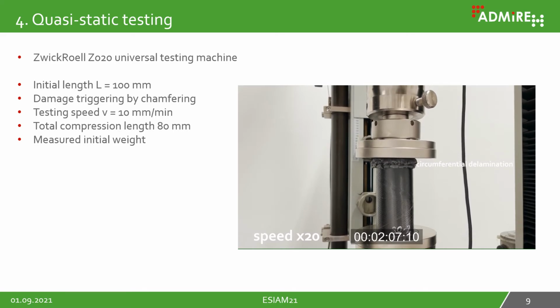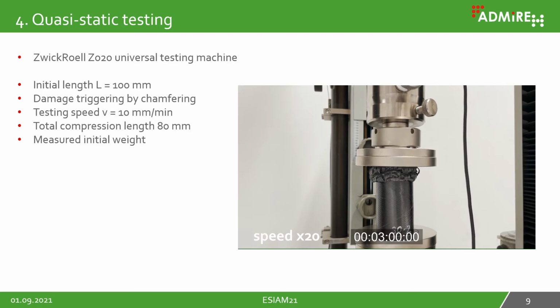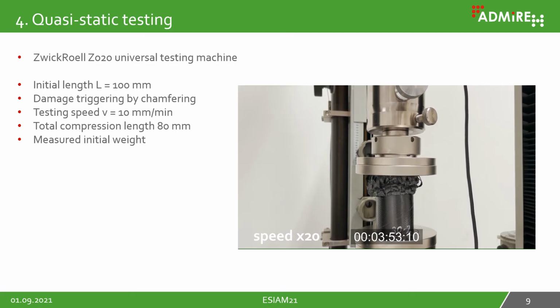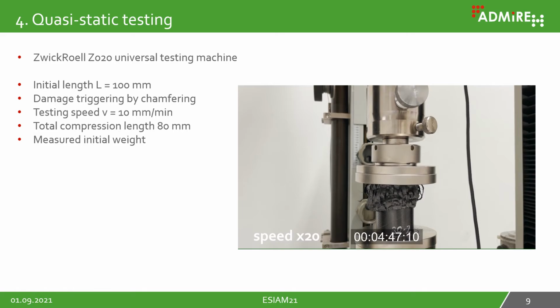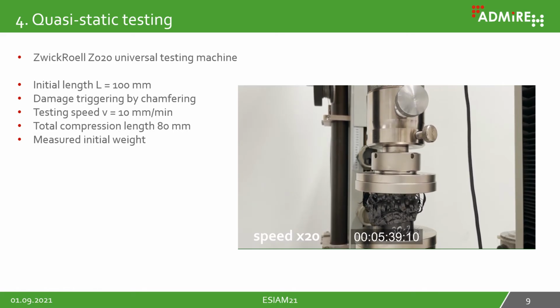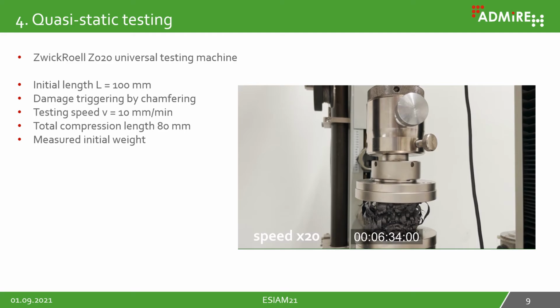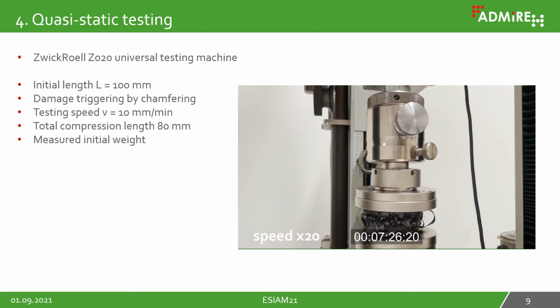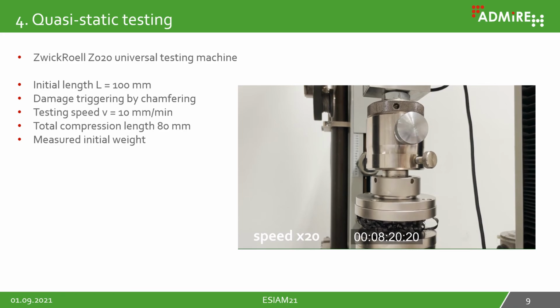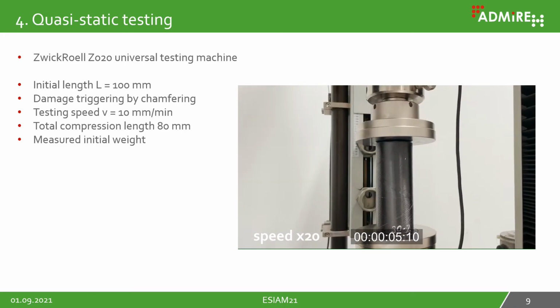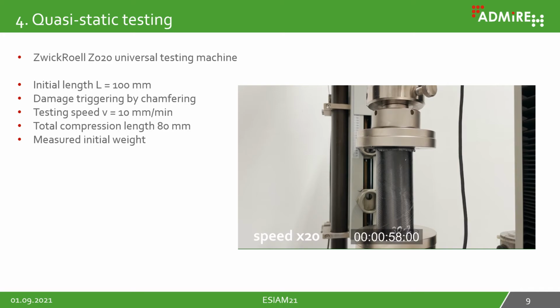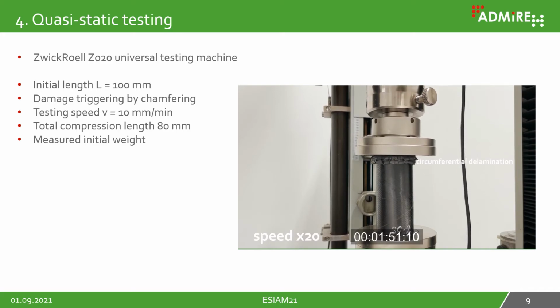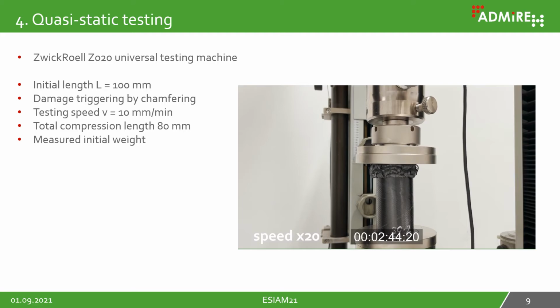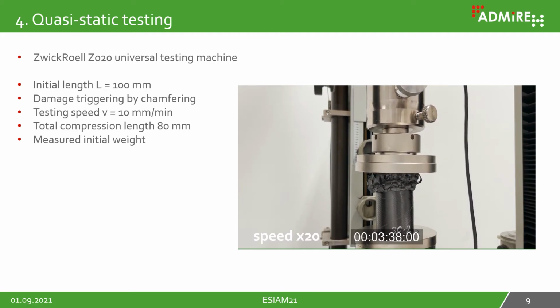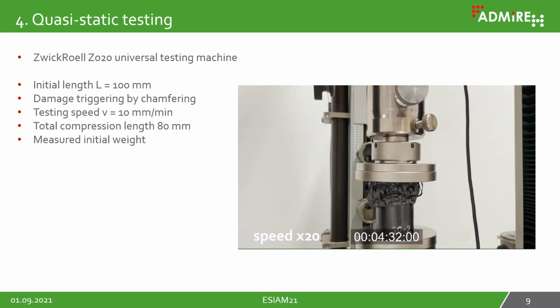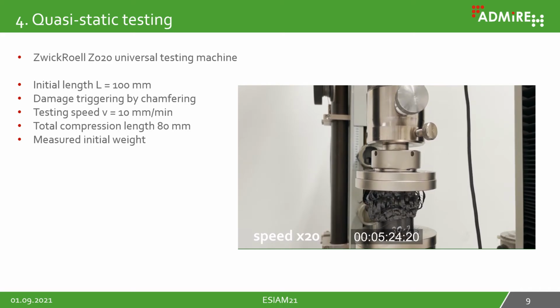The values of force and displacement were recorded to examine the energy absorption capability. A force displacement diagram was created from the data. On the right side, you can see the quasi-static testing of a CCF tube with a 30-degree fiber angle. It is sped up by 20 times. As you can see, the circumferential delamination starts and small petals are created during the process of compression.